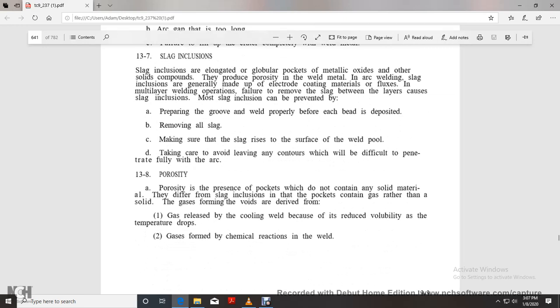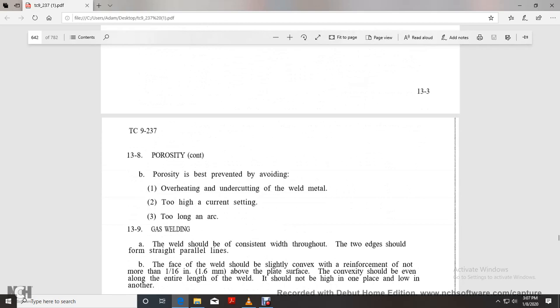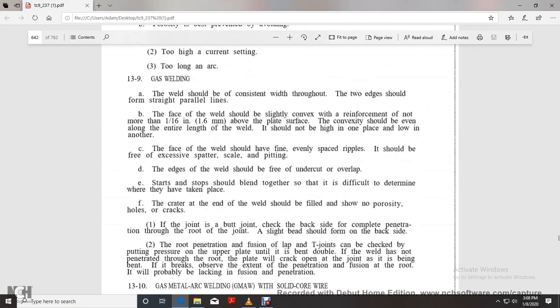Porosity. Porosity is the presence of pockets that do not contain any solid material, which is the difference from slag inclusion, a pocket that contains solid. The gas forming the voids is derived from gas released from the cooling weld because of the reduced volatility as the temperature drops, or from a chemical reaction in the weld. Porosity is prevented by avoiding overheating, undercutting, welding with too high a current setting, and too long an arc.